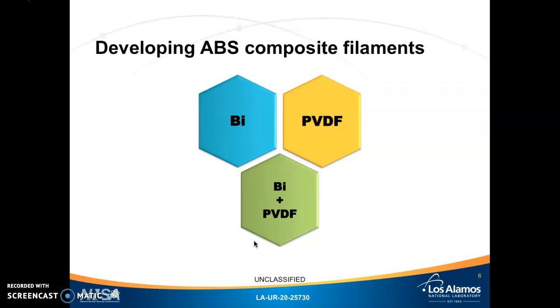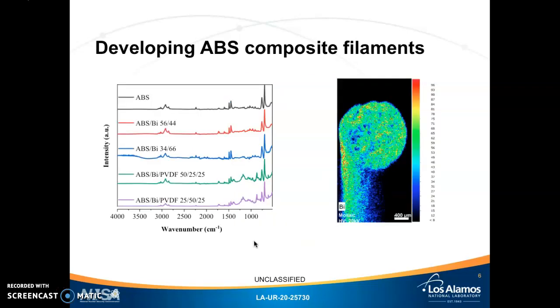Once we were successfully able to fabricate ABS composite filaments with PVDF and bismuth separately, all 3 were combined in different proportions to make a variety of printable composite materials. The FTIR image on the left shows peaks associated with the functional groups of each organic component. Observe that the top black curve representing ABS has peaks that all the other curves exhibit, thus demonstrating that ABS did not degrade in the process.